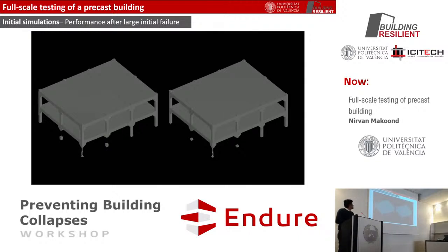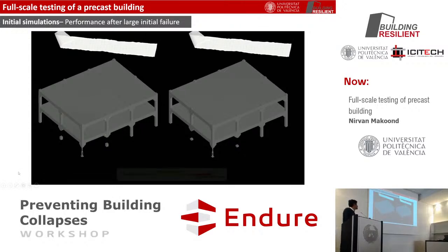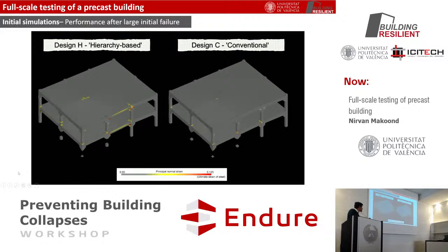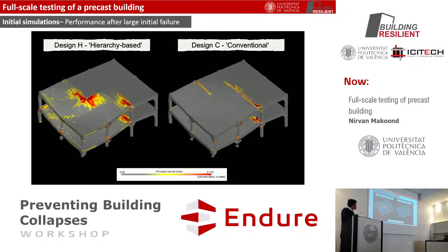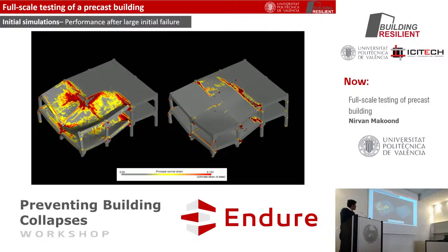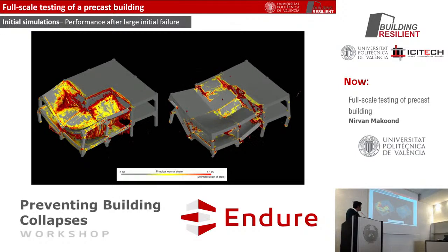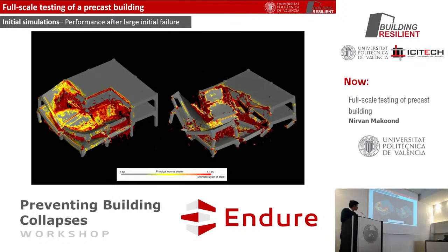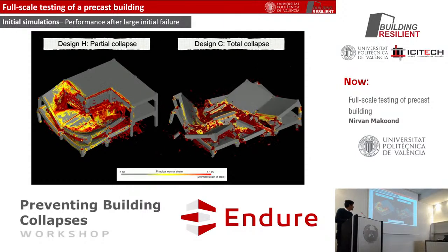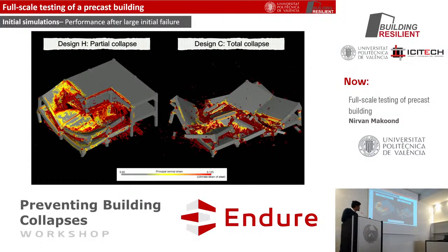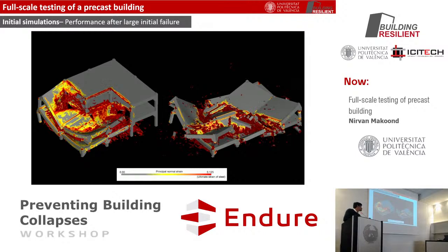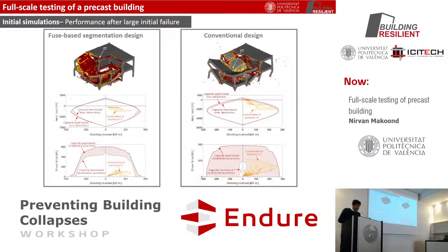However, after a large initial failure, involving the removal of the three edge columns supporting this corner bay, here we have the fuse-based segmentation design, which only results in partial collapse, whereas the conventional design leads to total collapse in this case.